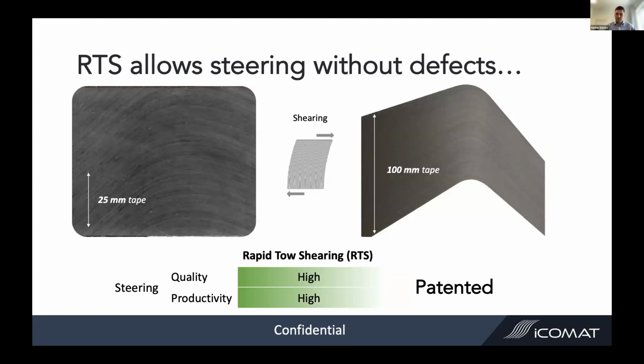So what is different with the Icomat process, or RTS? So instead of bending the tapes, we shear them. So as you can see in the image on the left, with a 25mm wide tape, we have a nice curvature going in there. There's no delaminations. Again, with 100mm wide tape, we have a good quality layup. So we have excellent quality and high productivity because we are using wider, more cost-effective tapes. We need fewer machine passes to lay down the material. And it's also material agnostic. So you can use thermoplastic, thermosets, dry fiber, pre-preg, and also bio and more sustainable fibers as well.